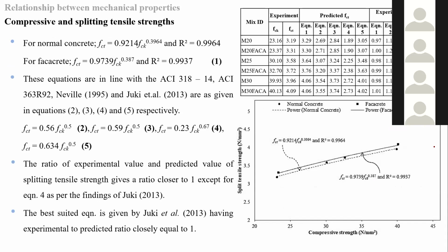Then split tensile strength, which is very useful for pre-stressed concrete applications. The higher split tensile strength is very useful for pre-stressed concrete applications. We achieved that also. Then flexural strength, which is used in the design of mixed concrete, so we wanted to check the flexural strength also. This is a numerical relationship developed between the mechanical properties, compressive strength and splitting tensile strength. These are mathematical models only. No need to concentrate more on this particular area.